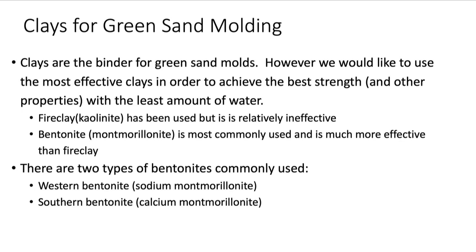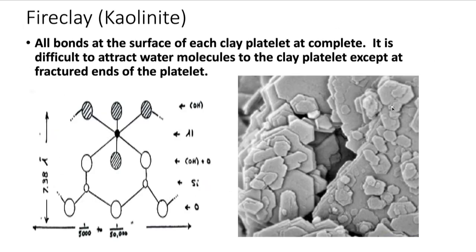Okay, so what actually is clay? Clay is these little platelets. If you look off to the right here, you see these little flat platelets. And by the way, they're really, really small and really, really thin. I believe they're just a few nanometers thick, or 1 nanometer thick. They're kind of like graphite. They're similar. They're strong in two directions, but really weak in the third direction. So they're kind of tricky, what's going on here.